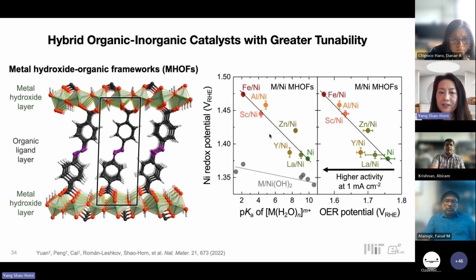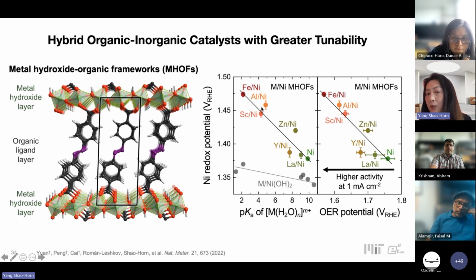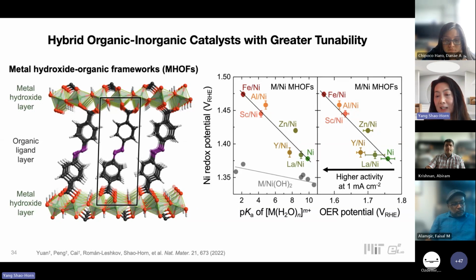that can catalyze OER. For example, we can look at these nickel-substituted catalysts, where if we substitute a different metal, let's say lanthanum, yttrium, zinc, aluminum, or iron, into the nickel site, we can change the nickel redox potential. If we make the redox potential more positive, that means it's more difficult to oxidize the nickel site. That translates to the binding of oxygenated species, OH, being weaker, and that's correlated with increasing OER activity on such a surface.